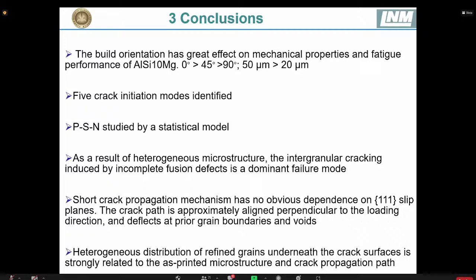And for the heat treatment, in the results I showed here, the specimens have not been subjected to any treatment. But as a comparison, later on we also did some heat treatment, and this result will be presented in the next conference and also published soon. We also changed the heat treatment and performed isostatic pressing, and we will compare the effect of the processing parameters on the fatigue behavior, especially on very high cycle fatigue behavior. Thank you. Yes, thank you so much.